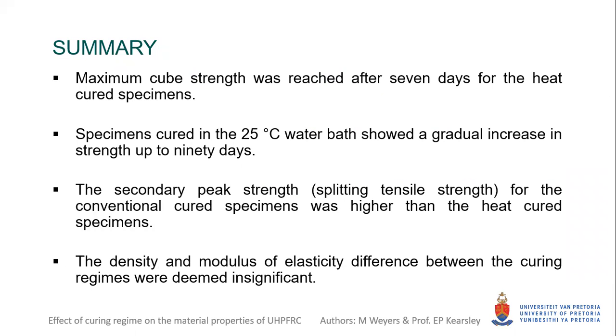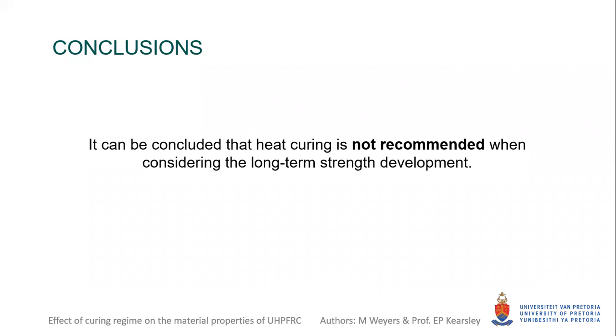In summary, a maximum cube strength was reached after 7 days for the heat-cured specimens, while specimens cured in the 25 degrees Celsius water showed a gradual increase in strength up to 90 days. The secondary peak strength, or splitting tensile strength, for the conventionally cured specimens was higher than the heat-cured specimens. Consequently, it can be concluded that heat curing is not recommended when considering the long-term strength development.